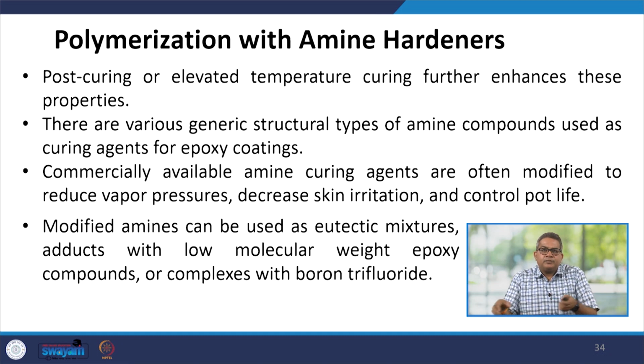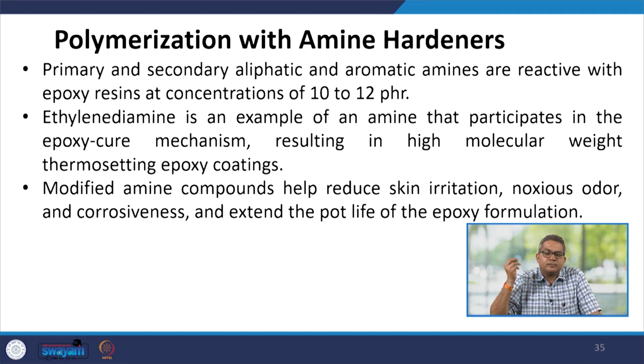Now, commercially available amine curing agents are often modified to reduce vapor pressure, decrease skin irritation and control pot life. These modified amines can be used as eutectic mixtures, adducts with lower molecular weight epoxy compounds, or complexes with boron trifluoride. Now, the primary and secondary aliphatic and aromatic amines are reactive with the epoxy resin at a concentration of 10 to 12 phr.